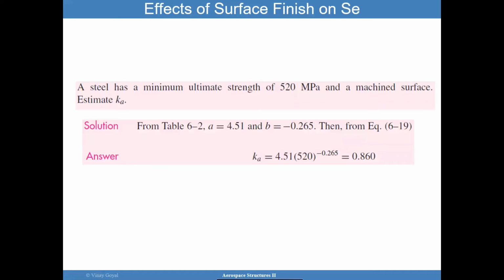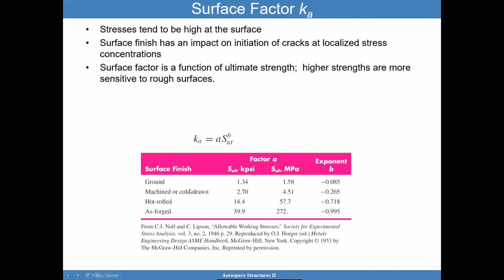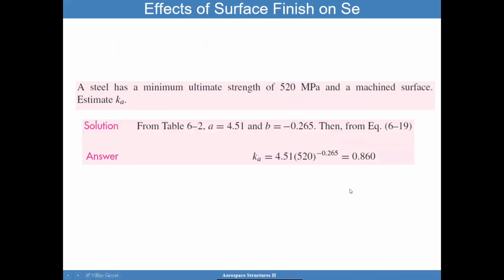As an example from Shigley's book, directly from that, if I have a minimum ultimate strength of 520 megapascals and a machined surface, what Ka should I use? Well, from this table 6.2, I have this condition, I have these values, so I plug it in and get a 0.86 factor.